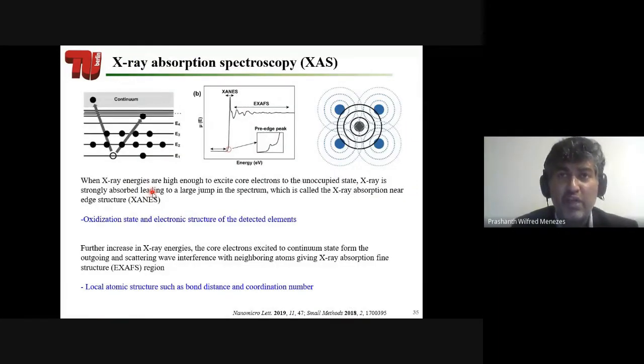Okay, as I spoke about real in situ condition, that means operando condition, where we could see what happens to the catalyst during the chemical reaction. Well, how could we check it? We could check from X-ray absorption spectroscopy. We have developed a method where we can measure X-ray absorption spectroscopy in real condition.